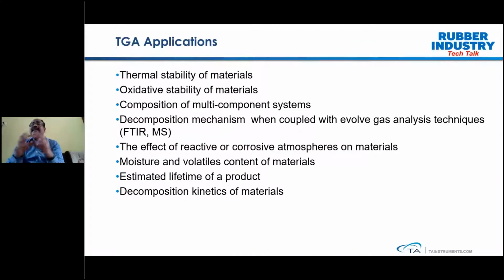Let's talk more about the key applications of TGA. As I said at the beginning, the major application is the thermal stability of the material. That is one of the key aspects, in terms of predicting the lifetime of your product. Suppose you have a polymeric material, a rubber polymer. How are we going to predict the lifetime of that particular polymer? In many applications the material can be subject to thermal and mechanical loading in real-world conditions. But here the TGA can give you information about how stable your material is going to be with respect to temperature.